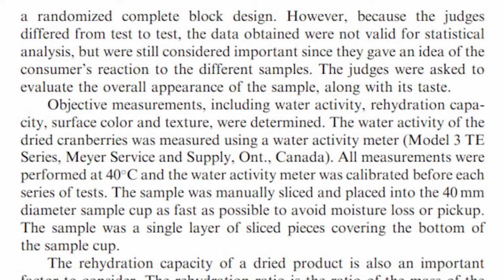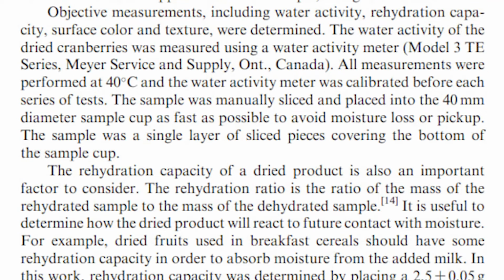Judges were asked to evaluate the overall appearance of the sample, along with its taste. Objective measurements, including water activity, rehydration capacity, surface color, and texture, were determined. The water activity of the dried cranberries was measured using a water activity meter, Model 3 TE Series, Meyer Service and Supply, Ontario, Canada. All measurements were performed at 40 degrees Celsius, and the water activity meter was calibrated before each series of tests. The sample was manually sliced and placed into the 40 mm diameter sample cup as fast as possible to avoid moisture loss or pickup. The sample was a single layer of sliced pieces covering the bottom of the sample cup.